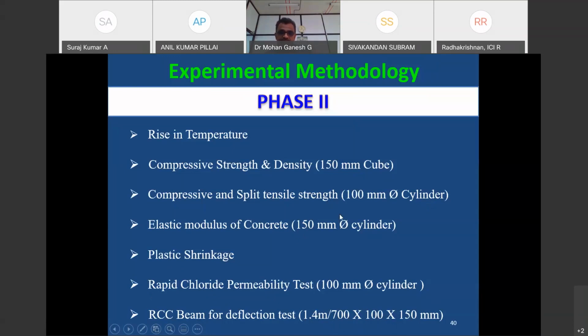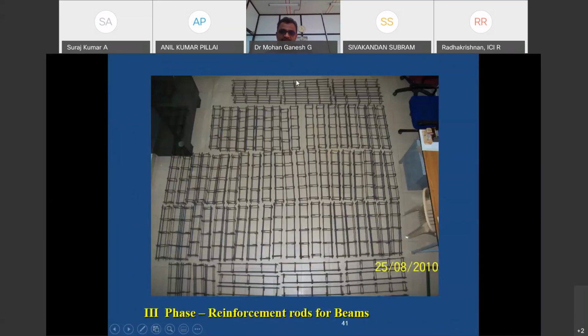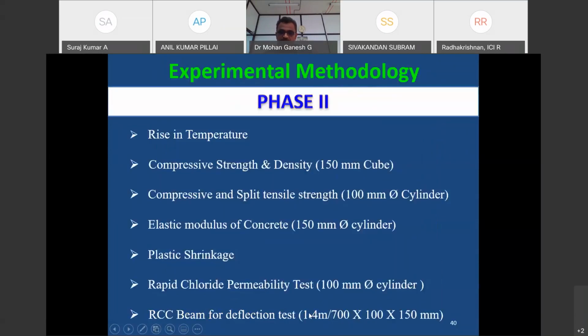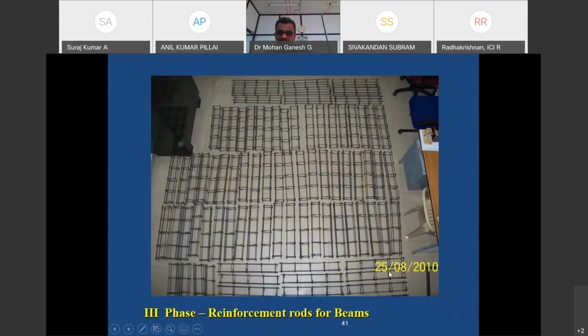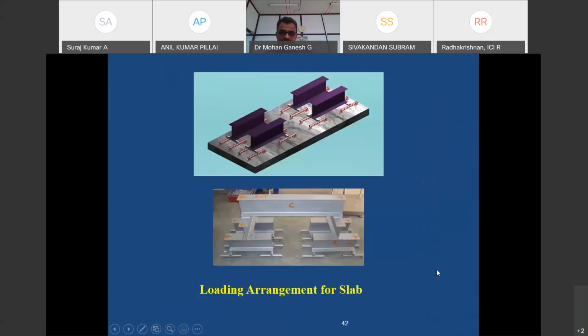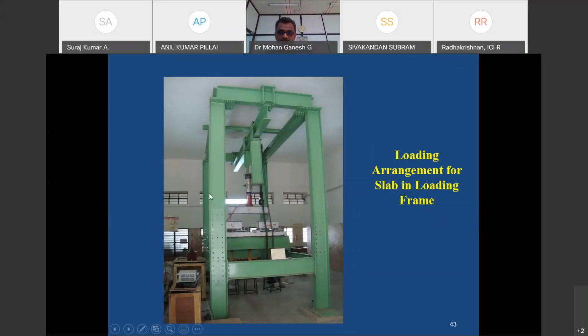The reason for this is that we have used the flexural mold for making this beam. So this is another pictorial view. More than 100 beams we cast for each category, either the 0.7 meter category or the 1.4 meter category. This we did in the year 2010. And for conducting the large scale test, this is a spreader beam arrangement. The slab we cast like this, and we want to apply the UDL load. Instead of going for knee braces, we made the spreader beam arrangement, and we have applied the loads. This is another pictorial view of the loading arrangement which we did at our lab.